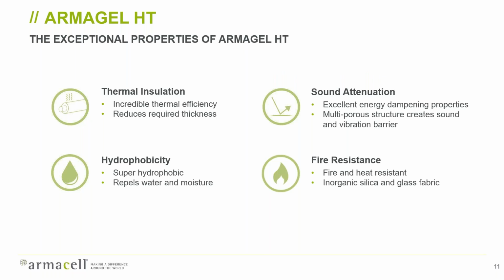Those properties in particular are very, very good thermal efficiency, excellent sound attenuation. As I said at the start, you can reduce the thickness of acoustic systems, and that's quite significant. It's super hydrophobic, and for all of those who are concerned about corrosion under insulation, we're really worried about how do we keep water out. Well, it is very, very water repellent, and again, you'll see that later on. And being made of inorganic silica and glass fabric, it has very good fire resistance.